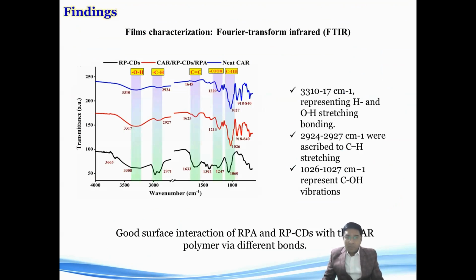When the films are formed, these are the RP series: the carrageenan with carbon dots, the carrageenan with anthocyanin added films, and the neat carrageenan films. What we have found is that both of the added ingredients have very good surface interactions with the carrageenan, and they perform their role in a very good manner, and the results are very good. Here, the different surface interactions, the chemical reactions, the vibrations, the stretchings, we can see these are carried out by using FTIR.